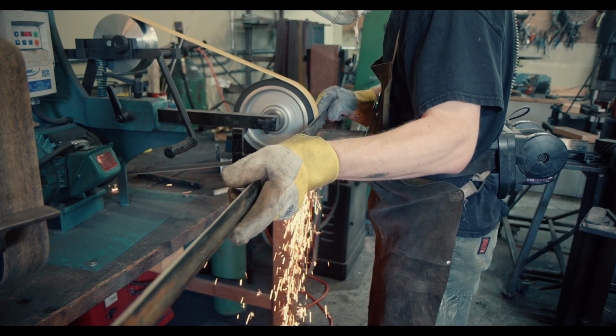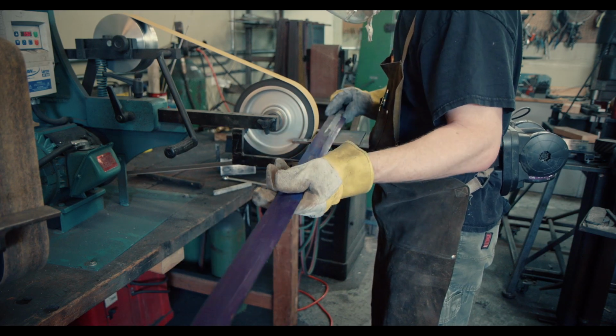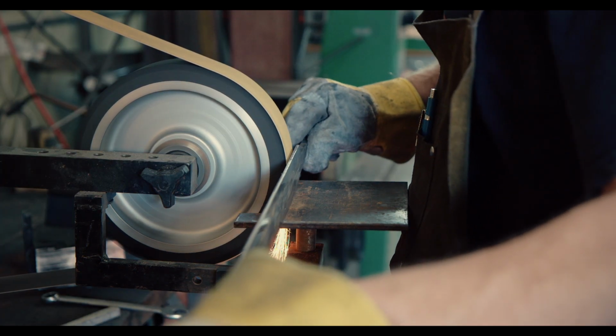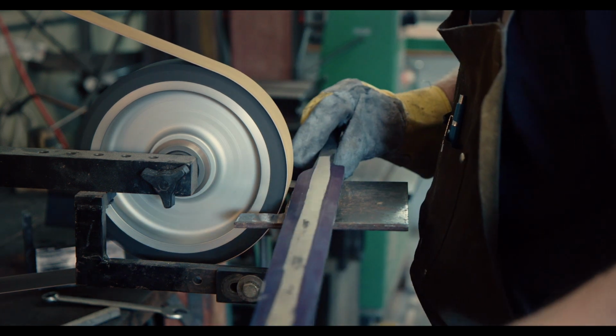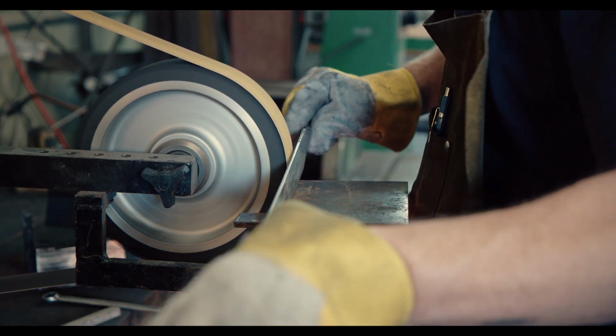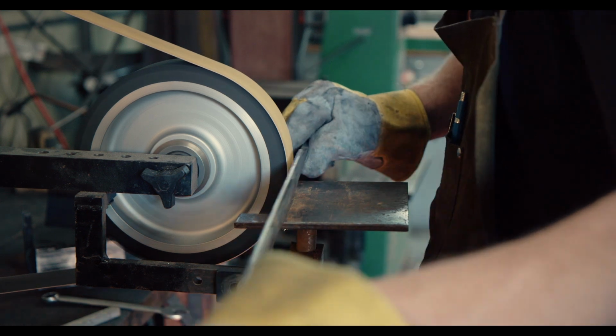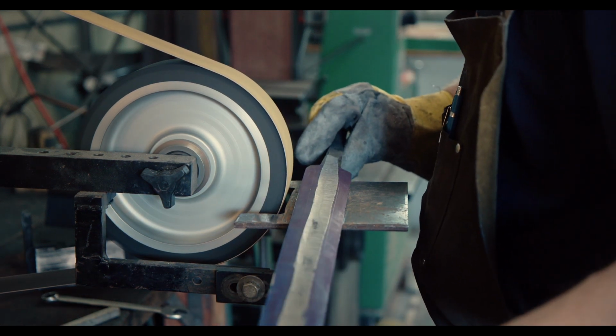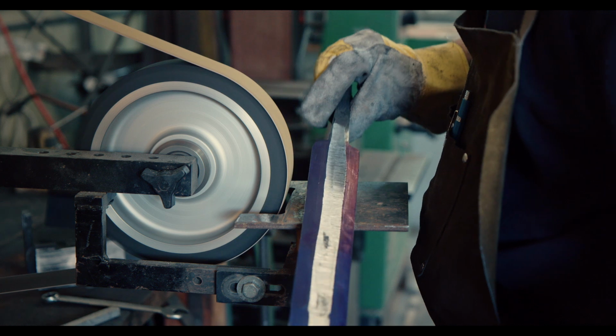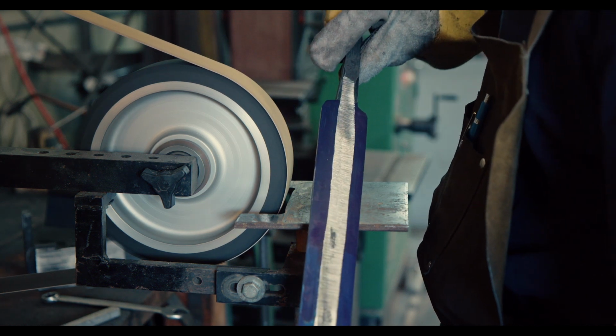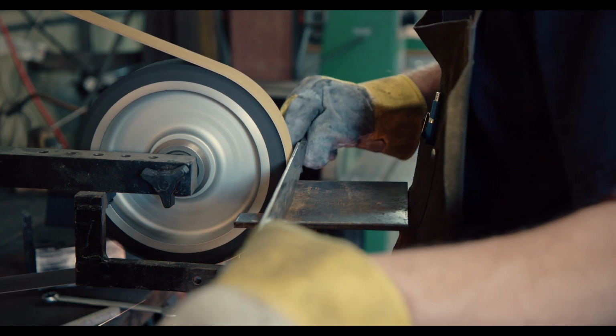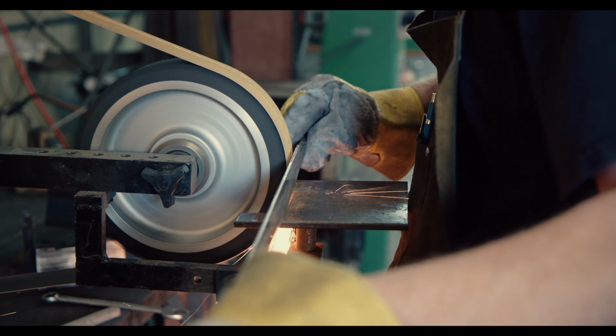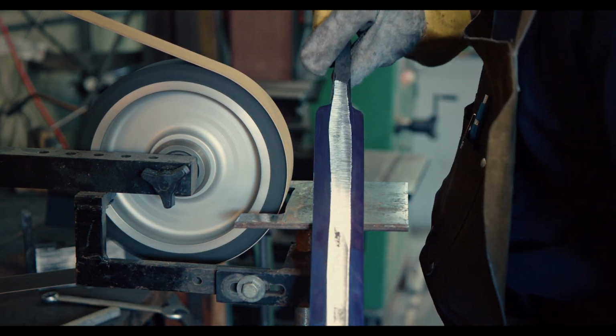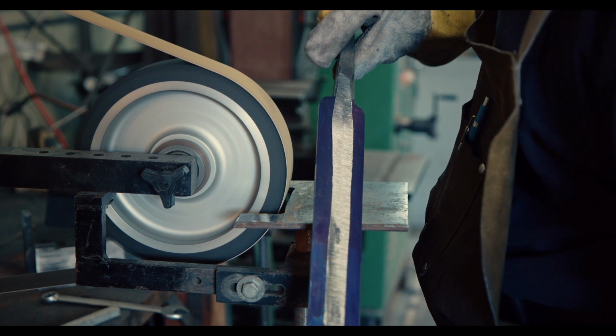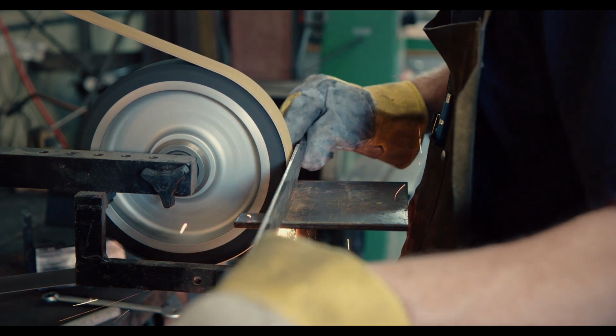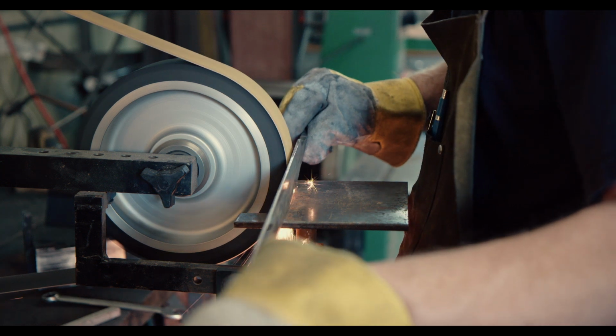Establishing the fuller on the grinding wheel is a delicate operation. I usually apply layout fluid and then carefully scribe a line that shows me where I need to stop grinding. Once the initial fuller has been established, it becomes a little bit easier to follow the lines by hand. Since the wheel will create a circular fuller shape, I sometimes employ a rocking motion to flatten the bottom of the fuller.